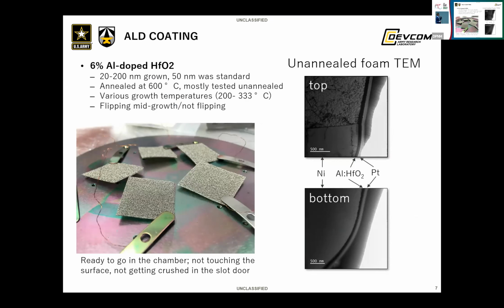We tried a bunch of various growth temperatures, and this is something I want to talk about real quick. Our ALD chamber is built for wafers, and I'm trying to put metal foams in there. So it's got a slot that's about 1 centimeter tall, and I also can't let the foams touch the surface at any point during the process. So they all had to be carefully cantilevered above the surface. Now, heat comes from the bottom platen, and the foams are only touching right here. So we measured thermal gradients of 50 to 60 degrees from the top to the bottom of the foam. That made it challenging to have the whole foam sit inside the ALD process window.